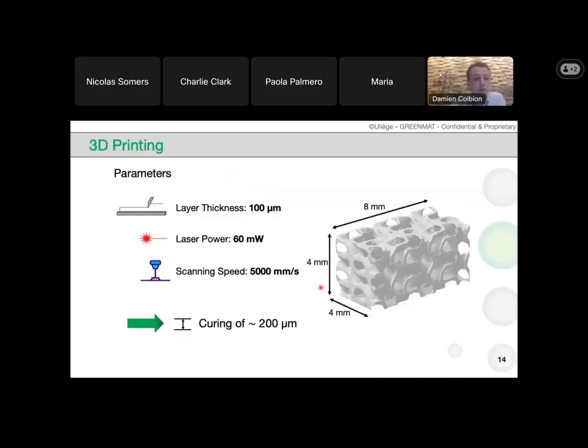So that's what I did for this part. We are printing gear-like pieces. For the depositions, we have a layer thickness of 100 microns. We decided to have a curing depth of 200 microns to have continuity in the layers so they can stick together. To do that, from the previous graph, we determined that the power of the laser required is about 60 milliwatts, and the scanning speed is about 5,000 millimeters per second.